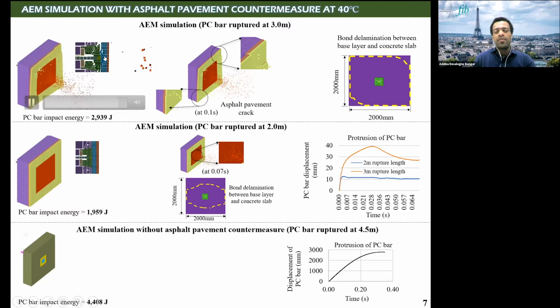only a thin layer of covering asphalt pavement was spalled off, and the PC bar was almost kept inside. In fact, there is some crack near the corner, but the pavement was still on the specimen. I mean, there was no fall down compared to the previous simulation. This is the interface bond delamination between the concrete slab and the base layer.